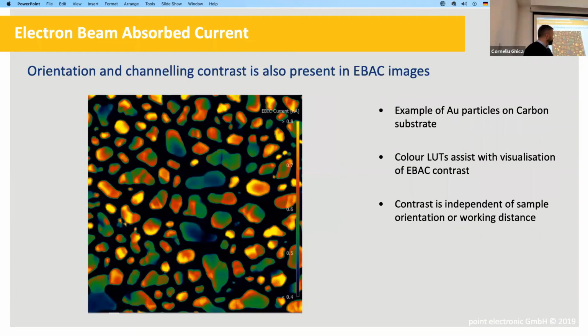Another standard sample is thin gold nanoparticles in carbon, and the image is in pseudo color. We also know the relationship between color and current because we measure the current at every point. What I'm trying to show is that in the gold nanoparticles we have orientation contrast. Orientation contrast shows not only in backscattered electrons, but also in absorbed electrons, because the currents are all related: current going in, current going out, the sum of all current. So all the signals are related.